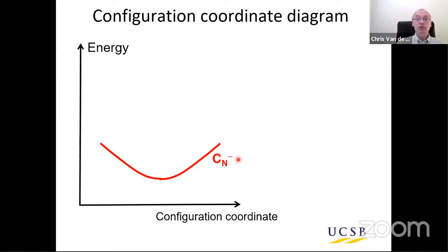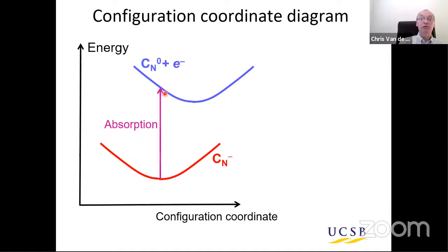So what we did was a systematic analysis of carbon. And for the optical transitions, what you want to do is create a so-called configuration coordinate diagram. You look at the two possible charge states that are going to be involved in this transition. Let's say that the negative charge state is the ground state. If you lift an electron out of this carbon level by exciting it with a photon, you can put it into a neutral charge state plus an electron in the conduction band. And as I said, that involves absorption of a photon. And then once you're in that neutral charge state plus the extra electron, you can go back to the ground state by letting the electron drop down again and letting the carbon become negative again. And that, of course, will be accompanied by emission of a photon.